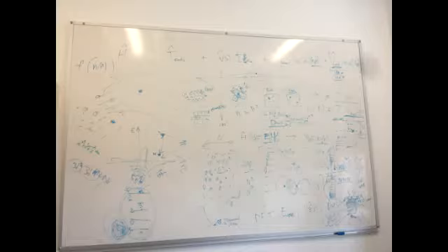And in a similar way, there are van der Waals interactions, especially in organic systems. Carbon, anything organic. So non-covalent interactions, just two molecules completely independent, like two benzene rings. There is an interaction between them, which is really poorly described by DFT, because this van der Waals interaction is a dynamic process of this molecule getting slightly more polarized temporarily.